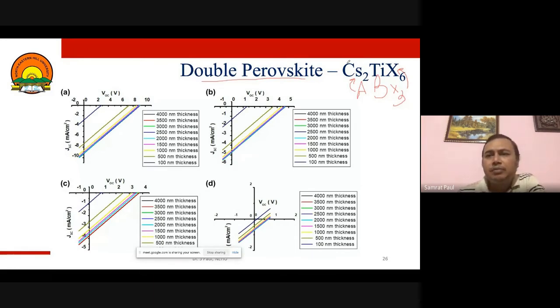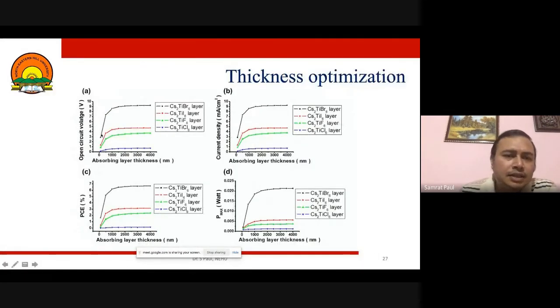So what we did is we made different materials. In place of X, we put different halogens and a combination of halogens, and these different halogens with different thicknesses we wanted to optimize. So we fabricated different thickness materials, from 100 to 4000 for different halogen types, and we found that with increase in thickness, up to a certain stage they increase the efficiency. And why, we understand, is that if the thickness is very thin, like 100 nanometers, it cannot capture all the photons that are exposed to it. Some of the photons, if it is 100 nanometers, will pass through the active layer. So we need an optimal thickness of this active layer, so that all the photons of different wavelengths can be absorbed properly. Which is also evident from this.